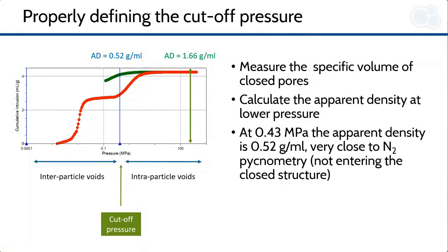This interpretation is valid whenever analyzing a powder material with intraparticle pores. By calculating the apparent density at a lower pressure and matching this value with the density obtained by nitrogen pycnometry, thus excluding the closed pores, we can get a proper cutoff value to distinguish the intra- and interparticle contribution to the total intruded volume. At 0.43 megapascal, the apparent density is 0.52 gram per milliliter, very close to 0.59 gram per milliliter by nitrogen low-pressure pycnometry.